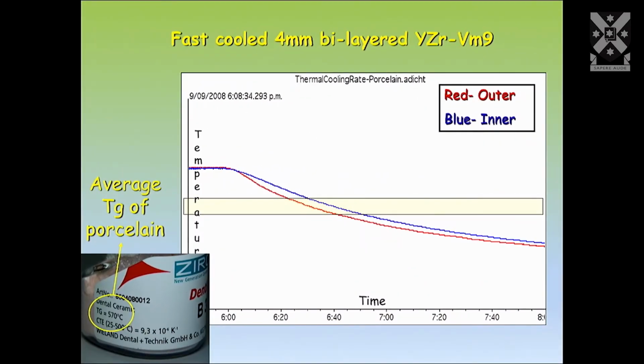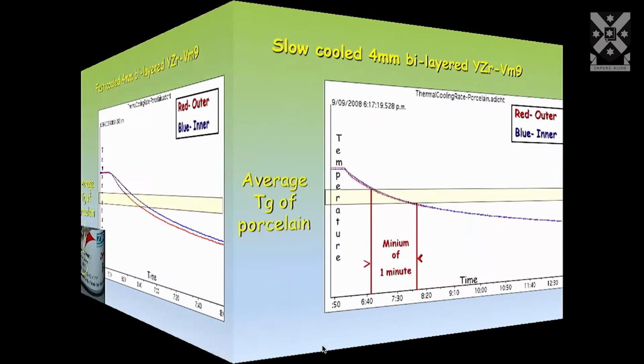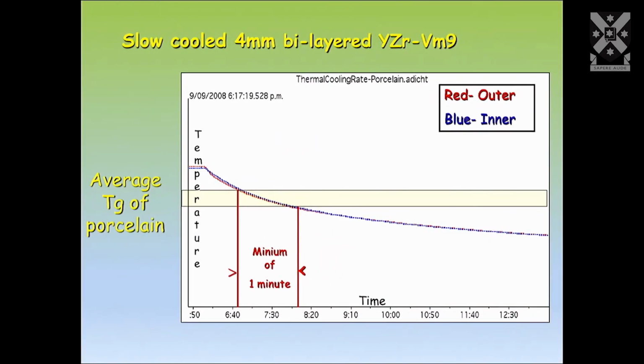And when we cooled it quickly, this little area in the middle here is the glass transition. You can see that the outside reaches the glass transition before the inside, and that sets up this residual stress of tension in the middle of the porcelain. But when we cooled it slowly, we didn't get that situation, and you don't get the residual stress.